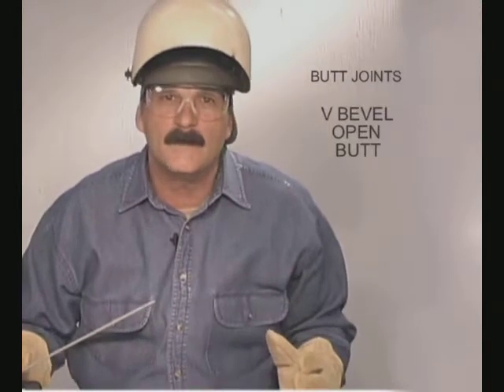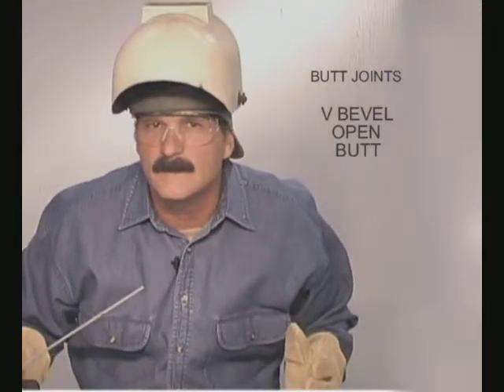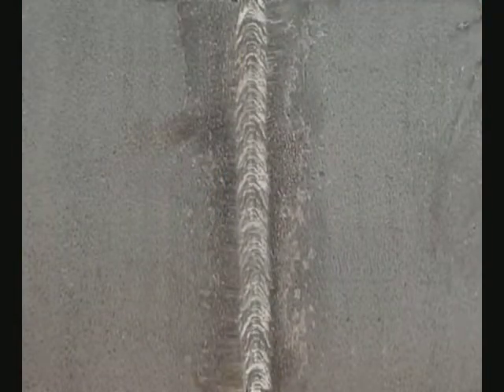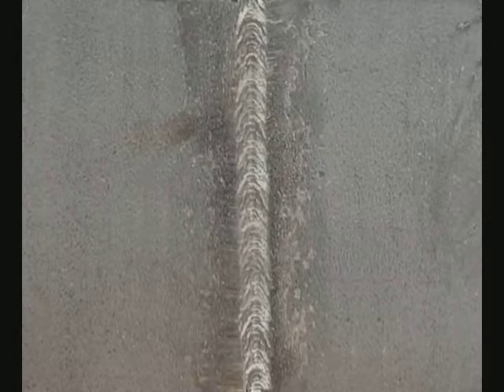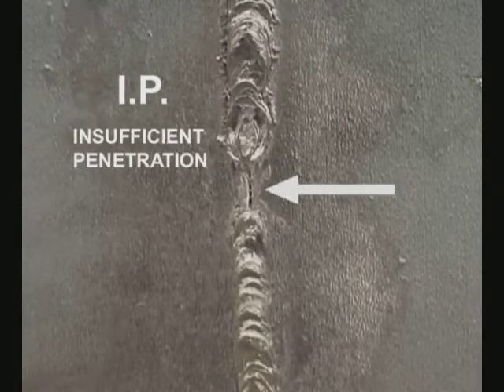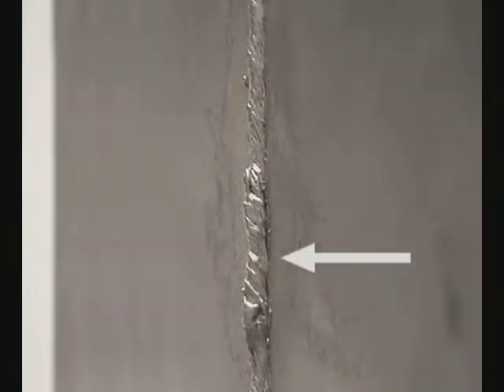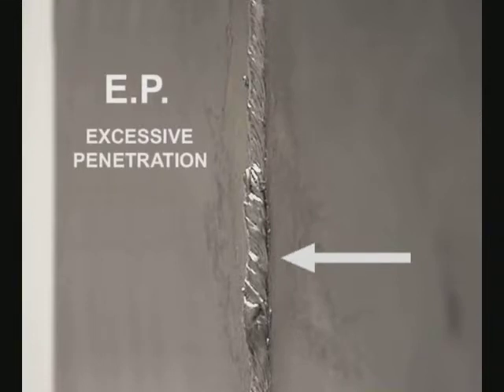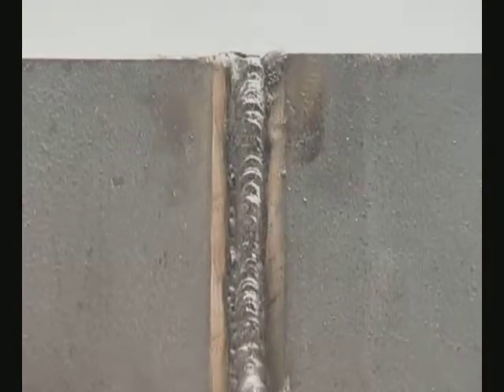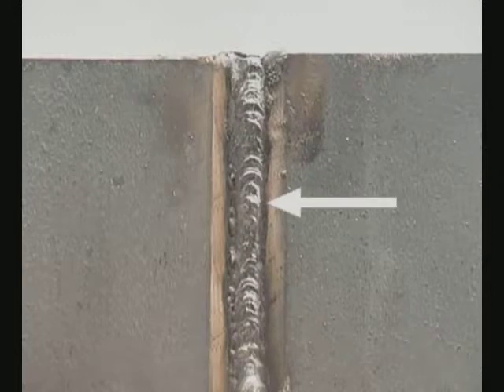Stepping the root uphill also works well when the gap is uneven with wide or narrow spots. The backside bead should be flush with the entire bottom edges of the bevels melted and fused. Any missed spots are called insufficient penetration. If the travel speed was too slow, the bead stacks up on the backside, causing excessive penetration. On the front side, because the rod was jammed right down against the metal, the bead will crown and undercut along both sides. Grind this out to avoid trapping slag.